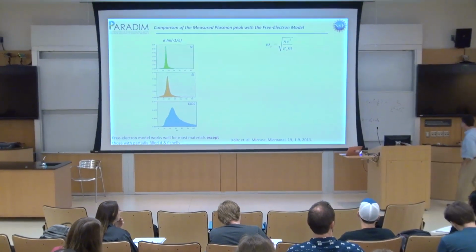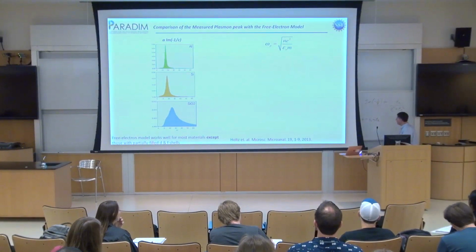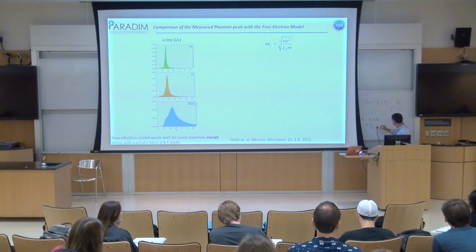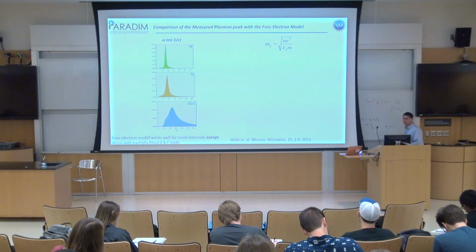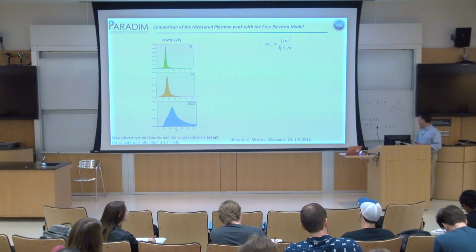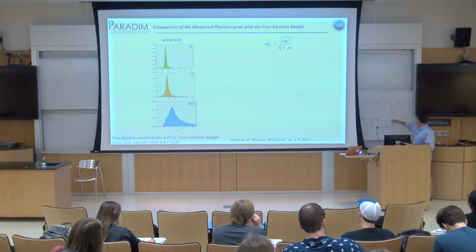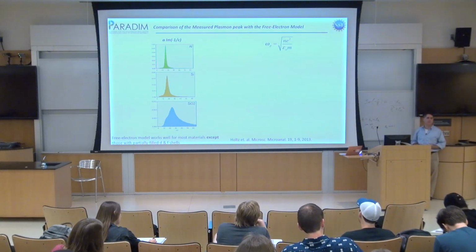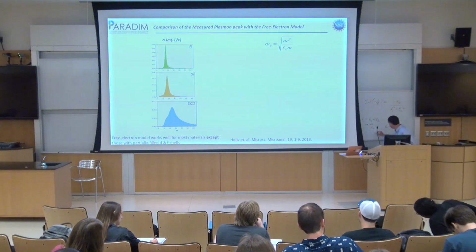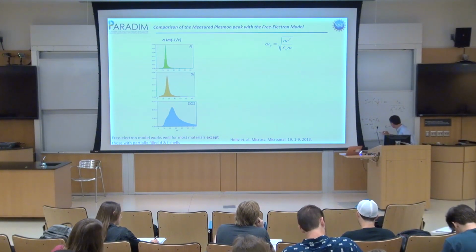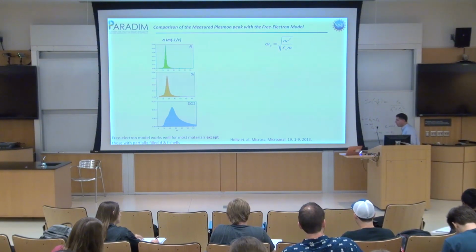For core loss spectroscopy, epsilon 1 is about 1, and epsilon 2 is very, very small. So under those conditions, the loss function is just basically going to be epsilon 2 when I take the imaginary part. So core loss EELS is just approximately going to be epsilon 2.